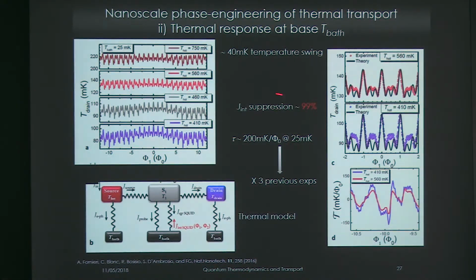And from our theoretical model, which was again an educated guess of how all the thermal losses behave in the system, we were able to demonstrate, you see here the fit to the temperature oscillation, that the interference part of the heat carrier can be suppressed in the same way, down to 99%. So this basically shows that whatever complicated shapes of multi-loop interferometers you can conceive electrically, this can be replicated in the thermal world, in the energy world, by taking into account how the system is exchanging with the rest. So it's a full demonstration that it's possible to do it in the same way. Okay.